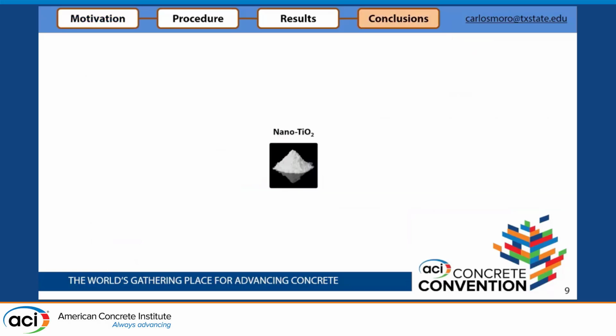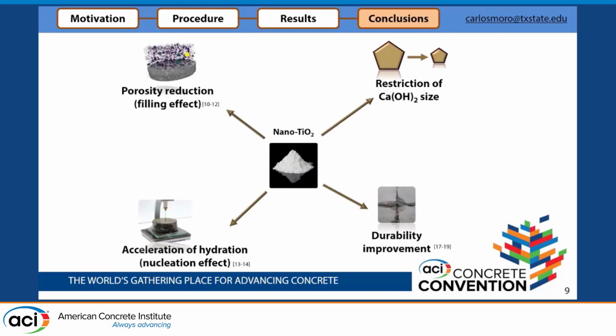So, this session is about nanotechnology, right? So we use nano titanium dioxide to do that. And this product has been used for porosity reduction, the filling effect, and also the nucleation effect because of the size of the nanoparticles.